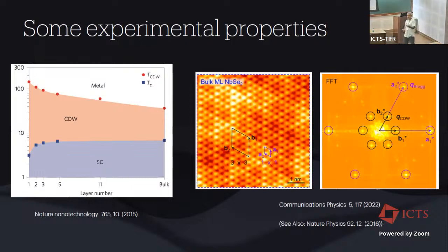This in itself is interesting, right? You don't have any significant suppression of the superconducting instability, and this particular point, which is in a log scale, it's not so clear, but this is a strong enhancement. This point would be around 33 Kelvin, and here we are talking about, I don't know, 135 or 140 Kelvin, enhancement of the CDW transition temperature. For the superconducting transition temperature, the bulk material TC is around 7 Kelvin, and once you go to the monolayer limit, the early work showed that the TC might be about 1 Kelvin, but now they have got cleaner samples. They say the TC is around 3 Kelvin, so it's not a significant change in the TC.